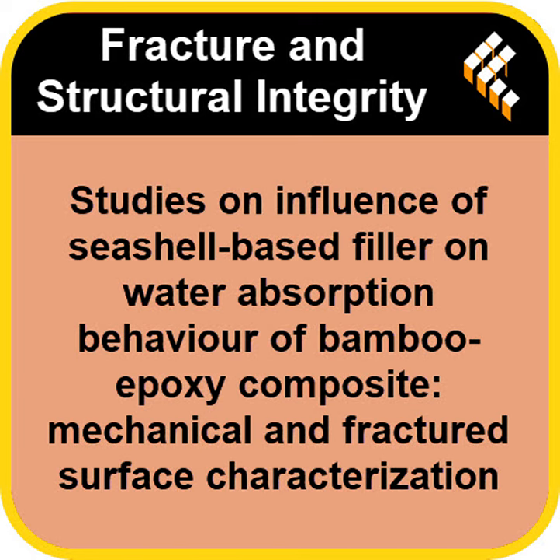How does that 30.4% reduction stack up against those fancier synthetic fillers you mentioned earlier? Very favorably, actually. That 30.4% reduction with 6% clamshells was reported as being better than what similar studies found for ceramic fillers, like aluminum oxide, which gave around 25.6% reduction, and silicon carbide, which is about 22%. So literally getting better performance from waste than from expensive, energy-intensive ceramics. In this specific context for water blocking, yes. It's quite remarkable.